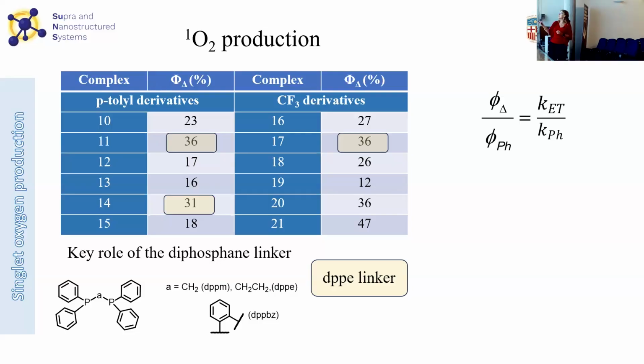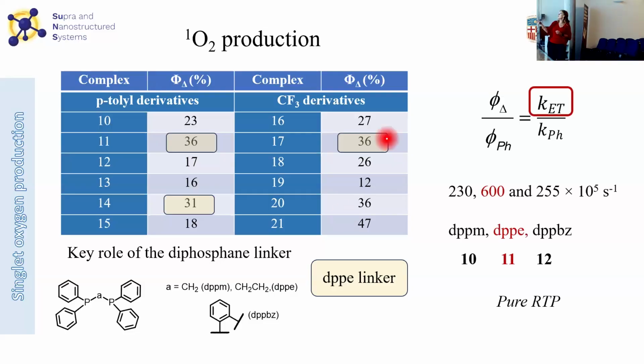And this was directly correlated to an enhancement of the energy transfer constant that can be calculated. This is the value with one methylene, with two methylene, and with a benzene, so clearly higher in the case of the dppbz.